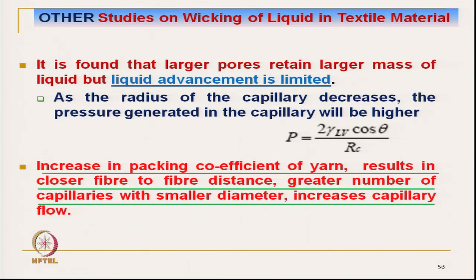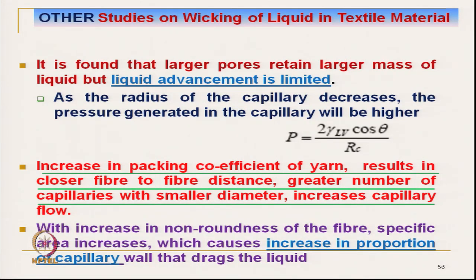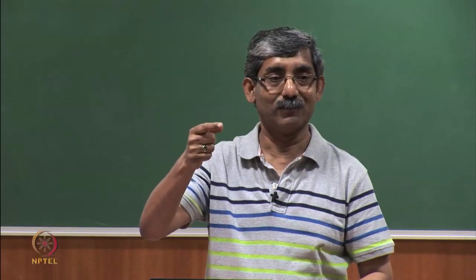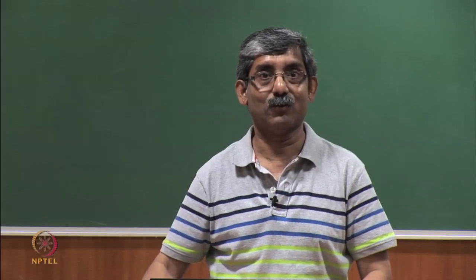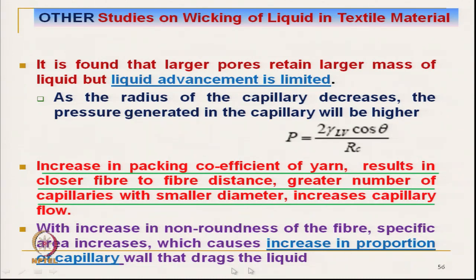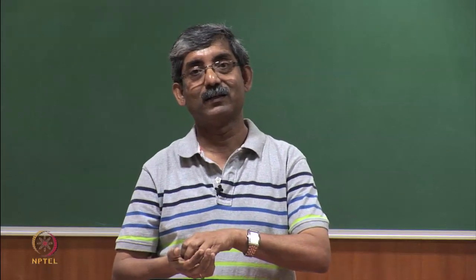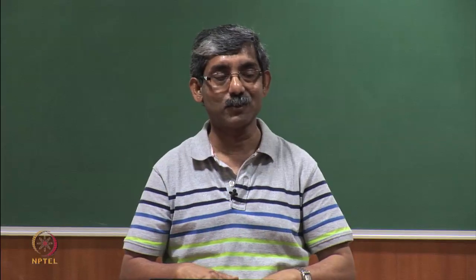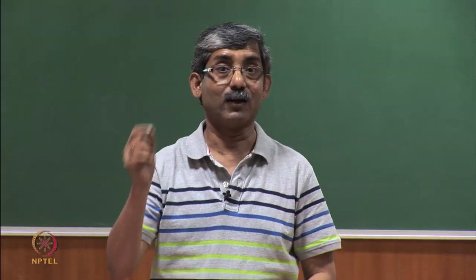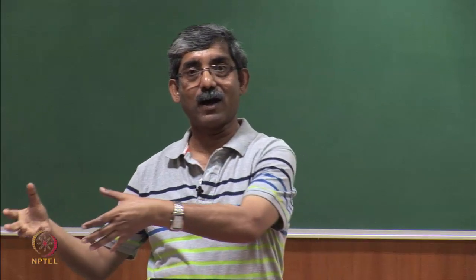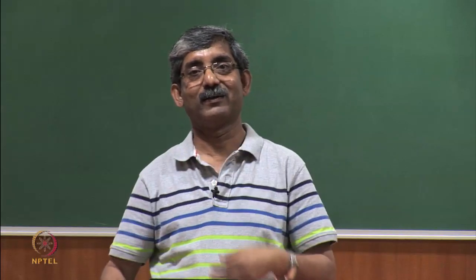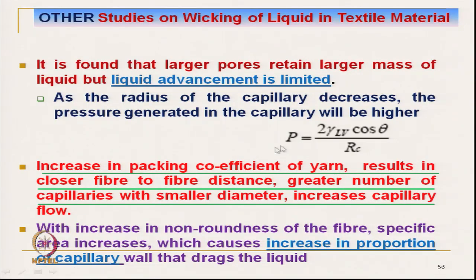Although the total porosity remains the same, the increase in non-roundness of fiber is very important. Suppose a filament is round, then its shape factor is less. With the increase in non-roundness of the fiber, the specific area increases, which increases the proportion of capillary wall that drags the liquid. That is why, with increased shape factor, wetting takes place due to apparent reduction in the wetting angle, and the capillary also gives a higher proportion of capillary wall, which enhances the drag. So, that is why the pressure increases.